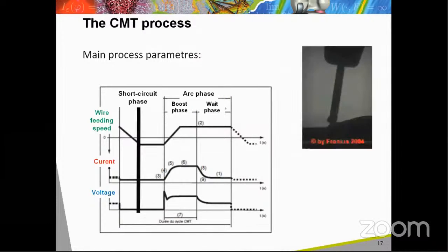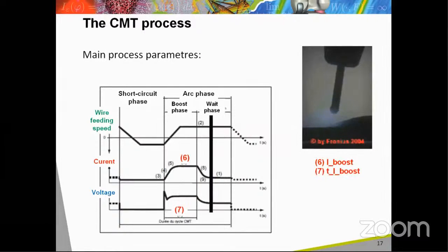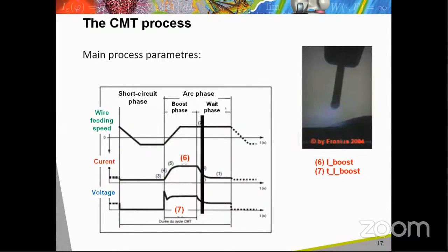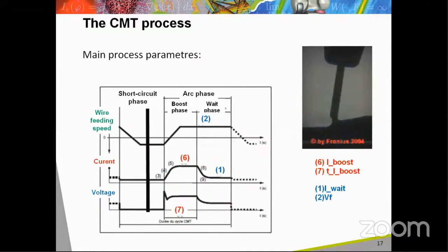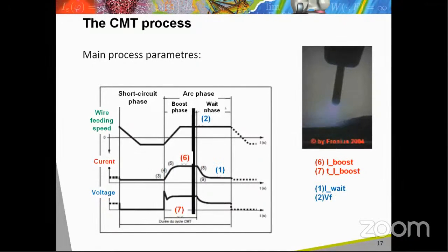One can see again on this slide the 3 phases of the CMT cycle and the main process parameters controlling these phases. The boost phase is mainly controlled by the boost current, I boost, and the pulse duration, T boost. The wait phase is mainly controlled by the wait current, I wait, and the feeding speed of the wire, VF. Finally, the short circuit phase is controlled mainly by the short circuit current, ISC, and also by the retract speed of the wire, depending on the feeding speed, VF.